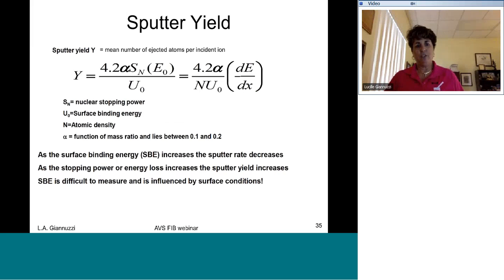So we've got the nuclear stopping, the surface binding energy, N is the atomic density, and alpha is a function of the mass ratio between the two. It's just given, again, by this function, where the energy loss is really important. So basically, as the stopping power or energy loss increases, the sputter yield increases. And just note that this surface binding energy is really difficult to measure and is greatly influenced by surface conditions.